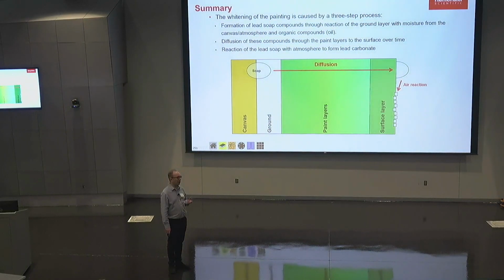In most cases you can mitigate for it, and it's generally not a quick process. I can think of one particular type of sample where we did see it degrade very quickly, but even then we were able to work around it. Usually when we're acquiring the data, we'll sit on the point and acquire several scans to get good signal to noise. In this case we couldn't do that, because if we stayed on the compound it would start to change chemically. But if we move around and collect data at several different points, we're limiting the exposure to the X-ray beam, and then we can average those points together and get a representative spectrum of the data. So that's the way we can do it.